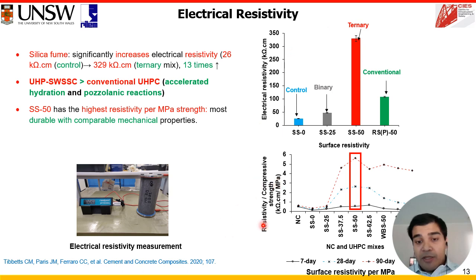We evaluated the resistivity per megapascal compressive strength and found that 50% substitution of OPC by SCM in marine UHPC produces the highest resistivity per megapascal compressive strength, which means this is the most durable concrete with comparable mechanical properties.